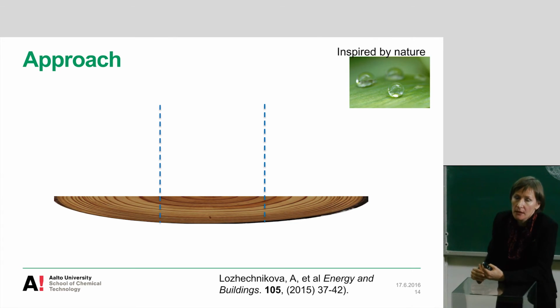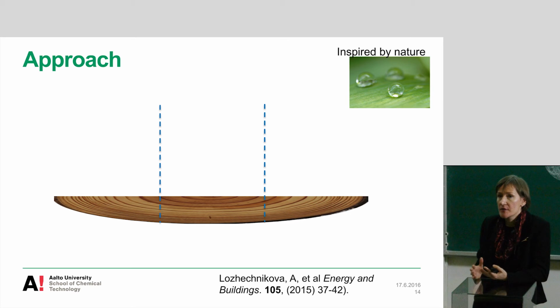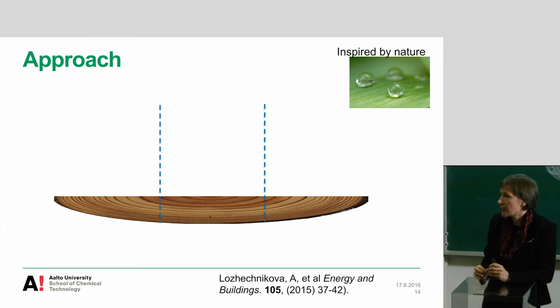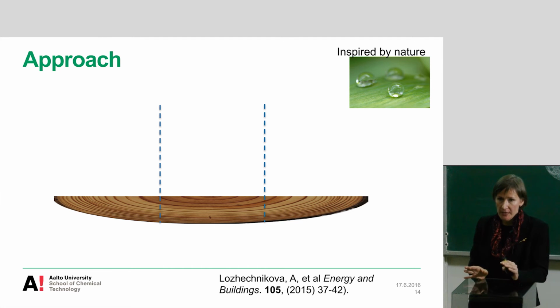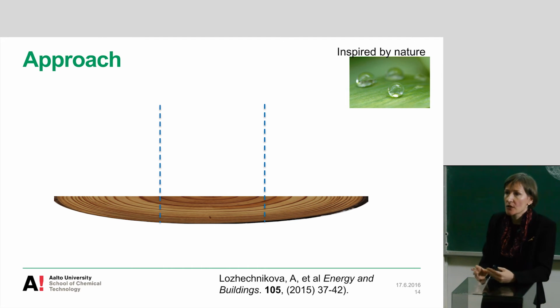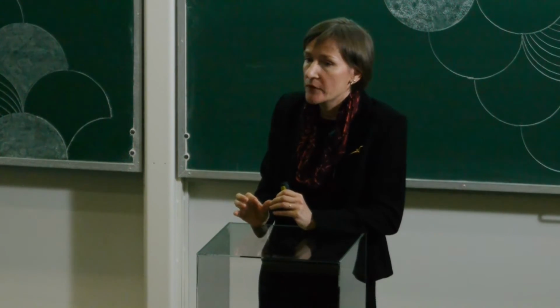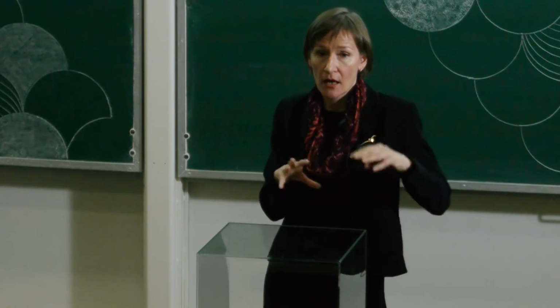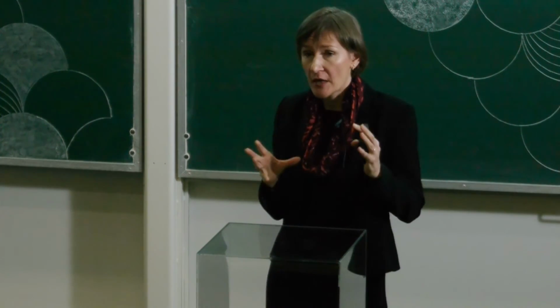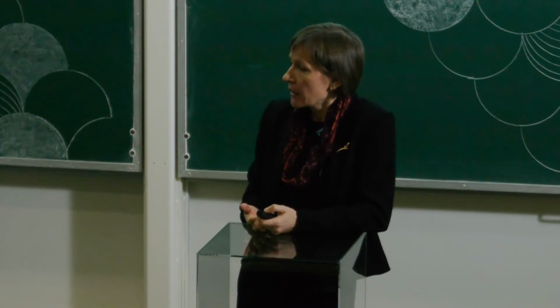Our approach was inspired by nature. If you have seen a lotus leaf, you can see, look at the water, it forms nice spherical droplets on the leaf. It doesn't spread at all. And that's because it has low surface energy, so it's hydrophobic. But it's not enough with the low surface energy. If you look with a microscope at this leaf, you will see that it has a hierarchical difference in roughness. So you need both the roughness and the low surface energy.